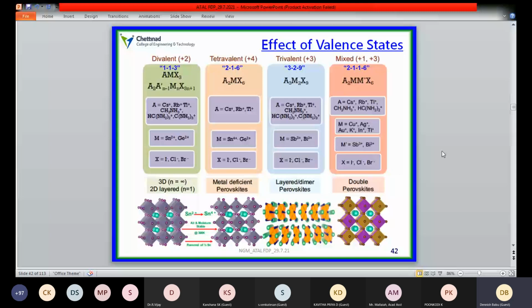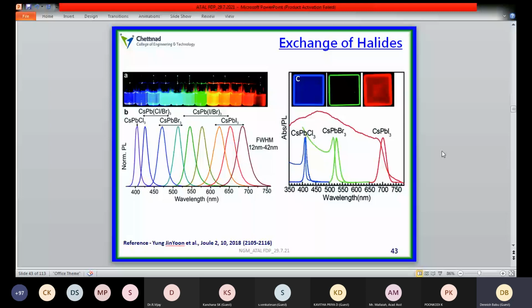By changing the halide system of cesium lead chloride, bromide, and iodide, we can easily fabricate and deviate the properties of the perovskite system, especially their luminescent colors. Cesium lead chloride exhibits blue color under the UV lamp. If we change the chlorine with bromine, the color changes from blue to green. Again, when bromine is replaced with iodine, the color changes from green to red. So by exchanging the halide atom in this perovskite system, we get different colors from the particular systems.